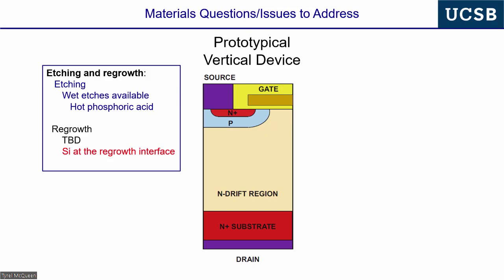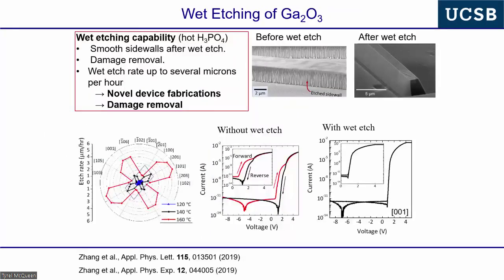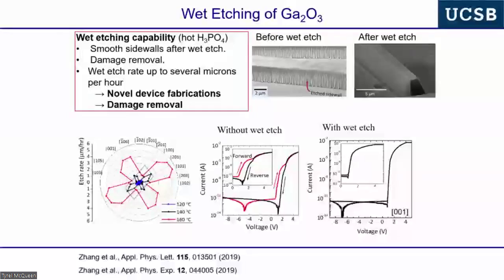And dry etching is approximately like ion implantation. The semiconductor is always damaged during dry etching. There's always ion damage. It's a problem. And so one of the beauties of gallium oxide, and this is something that we've worked on, is that we actually have a wet etch technology. So these are fins in our effort to make FinFETs, or trench MOSFETs, that we make in a wagon wheel pattern. So we're in low crystal symmetry, so we make a wagon wheel with spokes going in a wide range of